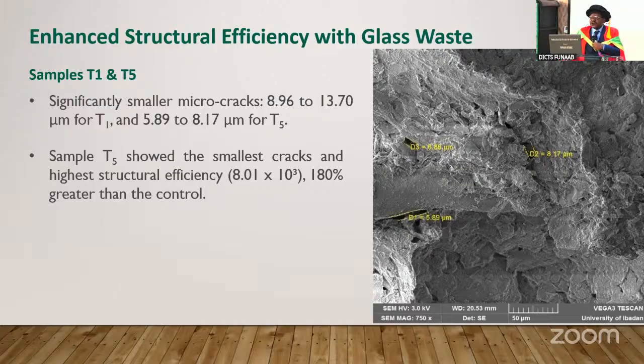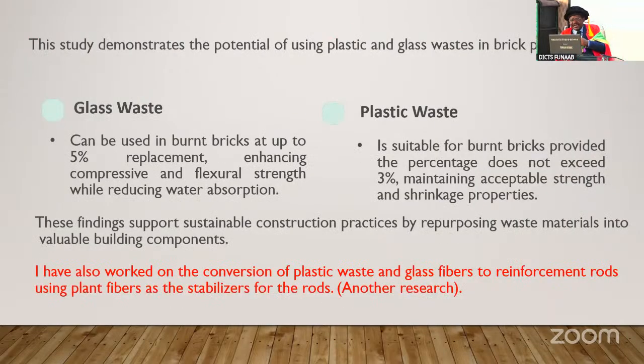This study demonstrates the potential of using plastic and glass waste in bricks. For glass waste, this can be used in burnt bricks at up to 5% replacement, enhancing compressive and flexural strength while reducing water absorption. For the plastic, it is suitable for burnt bricks provided the percentage does not exceed 3%, maintaining acceptable strength and shrinkage properties.